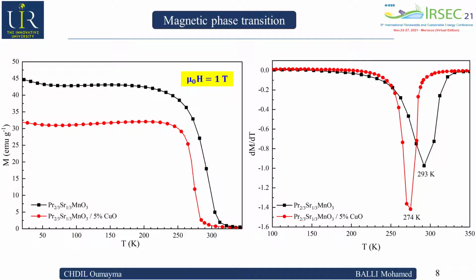On the other hand, here we have the magnetic measurements. From the lowest value of dM/dT as a function of temperature, we can estimate the Curie transition. By adding the copper oxide, we can observe that the Curie temperature decreased remarkably from 293 Kelvin to 274 Kelvin.